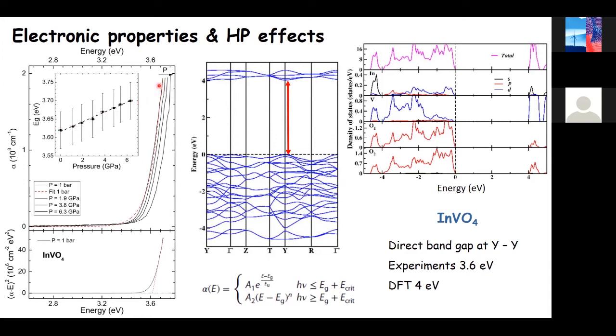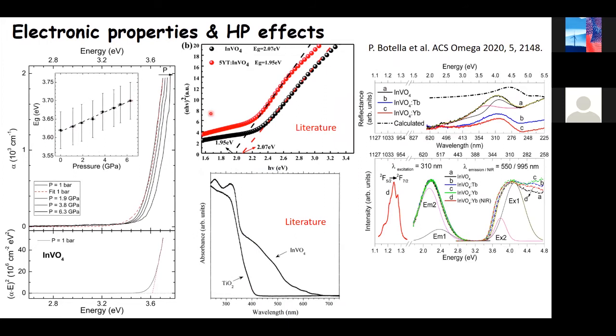So you can see here, we have a blue shift of the band gap with pressure, which you can also see here. So we clearly rule out these measurements indicating a low band gap, and we have shown that this is not the band gap, but this is the band gap, which is in agreement with our results. Indeed, we have also done reflectance experiments, which showed 2 band gaps, one around 3.6 and another a little bit above 4. And these are photoemission experiments also done by us, which give very similar energies for the band gap. So there is no doubt this compound has a band gap of 3.6 electron volts.